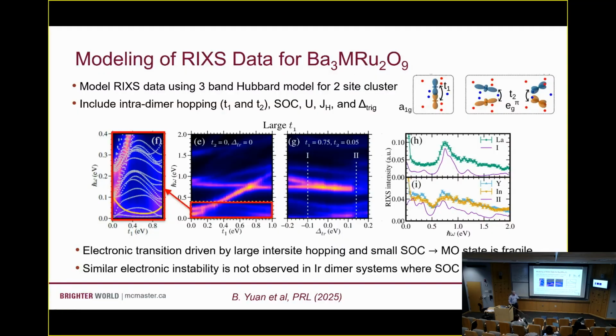Right? So if you go to the iridium versions of this compound, so there's a Ba3MIr2O9, you don't see these kind of transitions, like in the double perovskite case. All of these systems are locked in this spin-orbit dominated regime, where it doesn't matter what you're doing with the fine structural details, the states always look the same. Okay? So things are much more interesting and much more tunable when you go to this intermediate 4D limit.